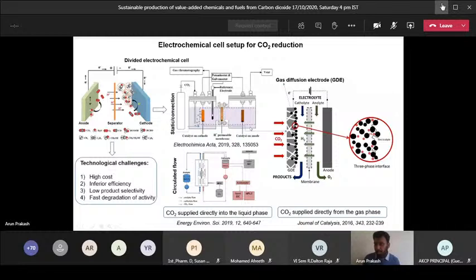So we use bicarbonate as the electrolyte, and when you use bicarbonate, it enhances the rate of CO production. So carbon dioxide will be reduced first to carbon monoxide through a 2 proton 2 electron process. So this process can be enhanced in the presence of a bicarbonate electrolyte. So dissolved CO2 is the primary source because you are going to reduce carbon dioxide. So CO2 is obviously the primary source of carbon. So whatever carbon is found in the solution comes from carbon dioxide, not from bicarbonate.